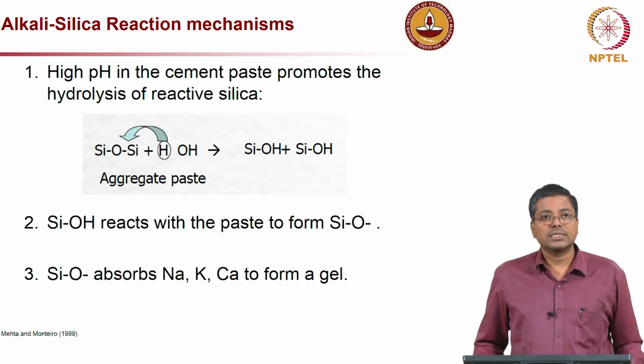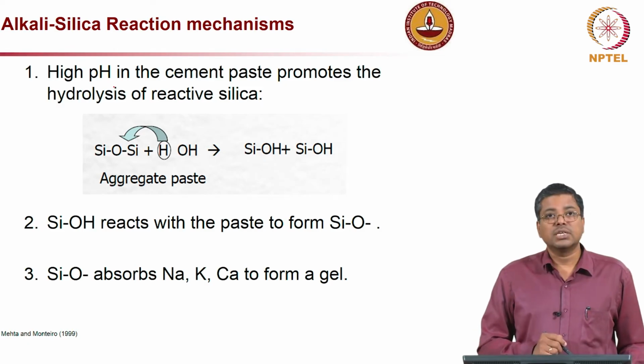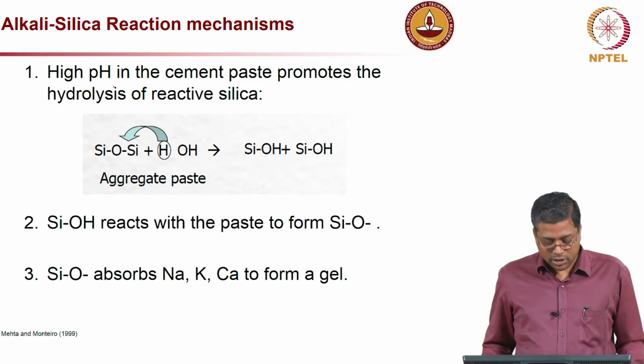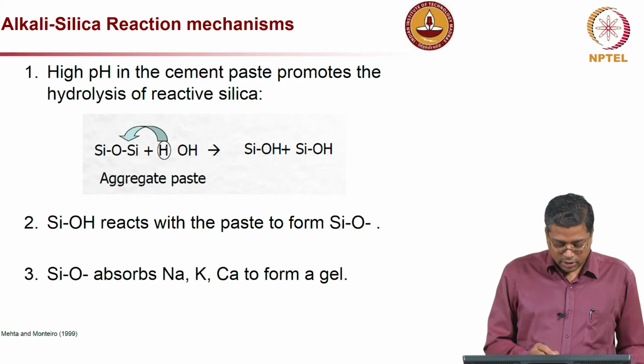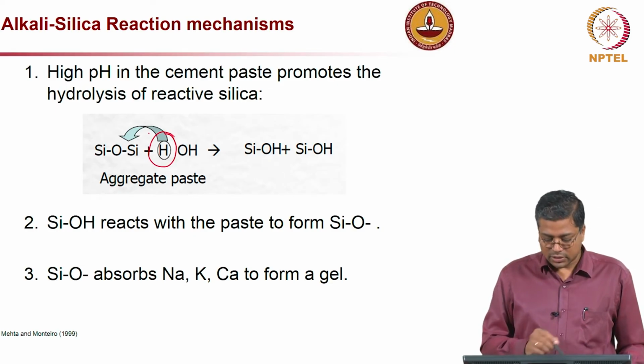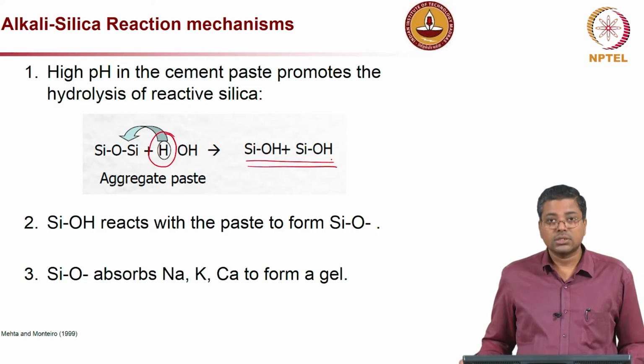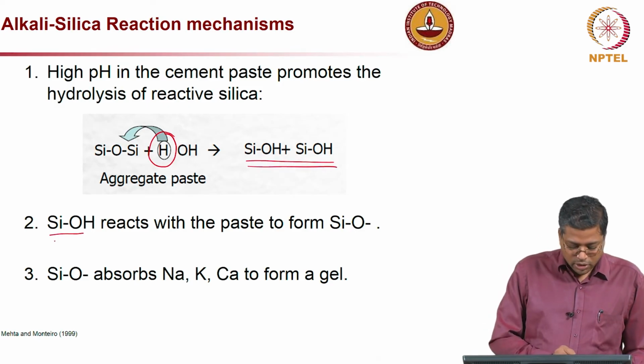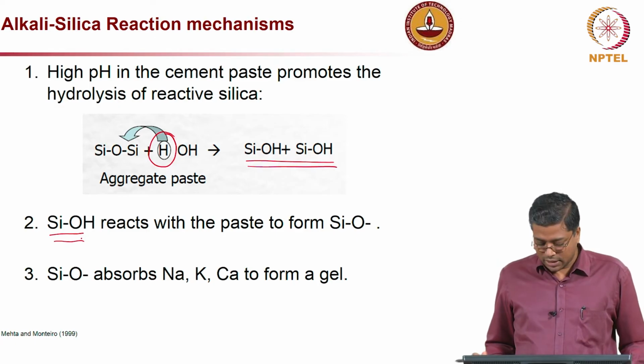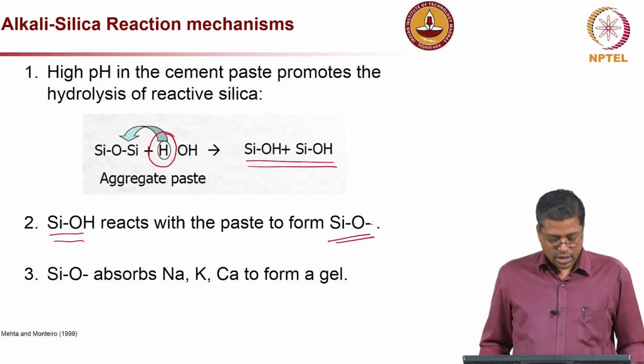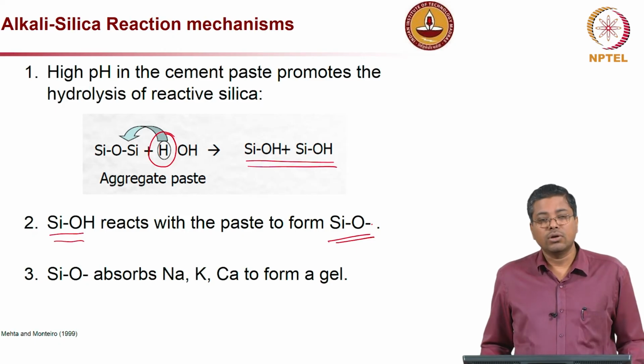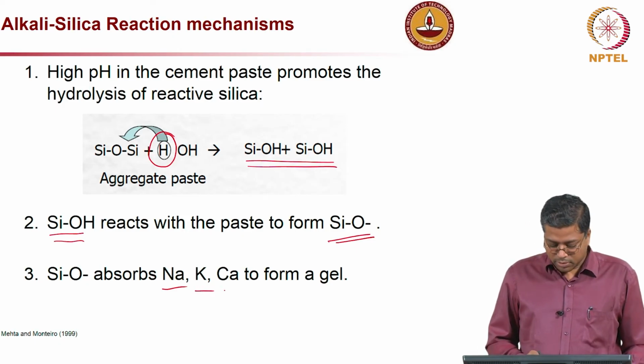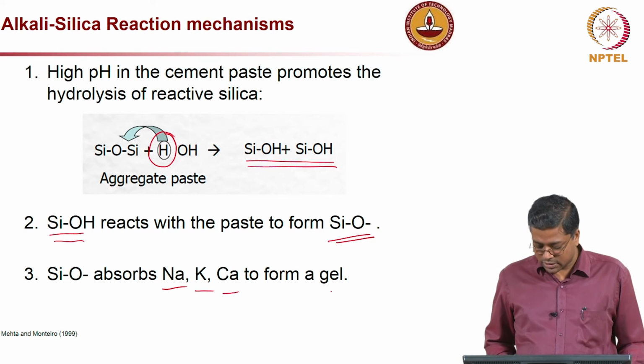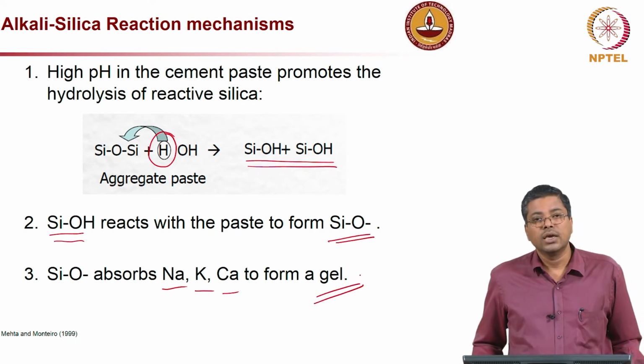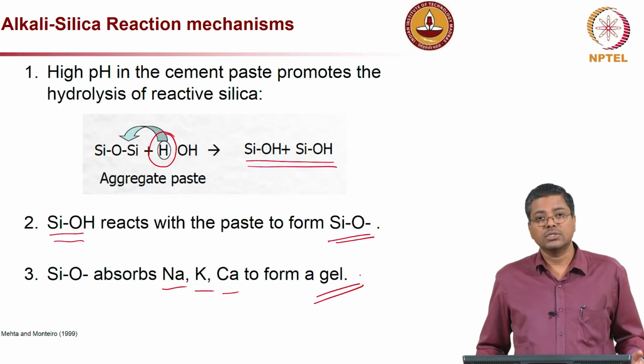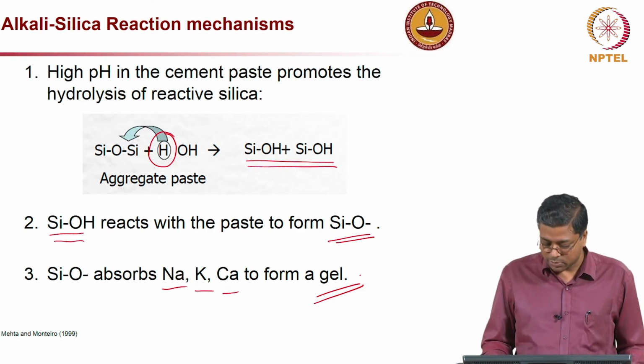Now, what is the reaction mechanism? The high pH in the cement paste promotes the hydrolysis of reactive silica, and it becomes SiOH bonds. Then this SiOH bond reacts with the paste to form SiO, which further absorbs or reacts with the sodium, potassium and calcium to form a gel. This is the gel which we are calling ASR gel, which is expansive in nature, or sometimes it absorbs the moisture and expands.